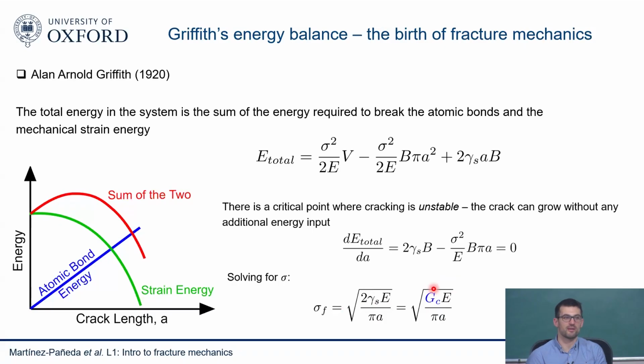So Inglis was right. The stresses can be infinite if you assume linear elasticity near a defect. However, it's not enough to get a high stress to propagate a crack. A defect would only grow where a critical energy is attained. So your critical load will depend on some sort of critical energy, a material property that will tell you how tough your material is. And I think at this point I'm going to do a 5-minute break.